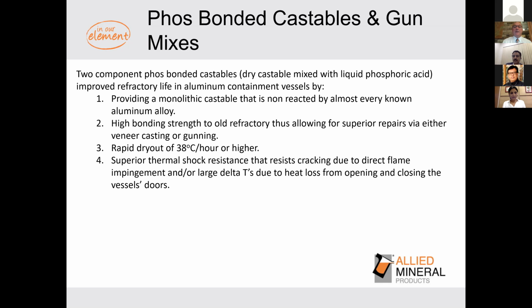We ended up doing veneer casting and gunning. We have both technologies to allow you to repair. We've achieved the rapid dry out of 38 degrees C per hour or even higher. And the other added benefit of the Phos bonded castable is superior thermal shock resistance. It's tremendous. And later on in my presentation, I'll show you a spalling test to show you how effective it is.